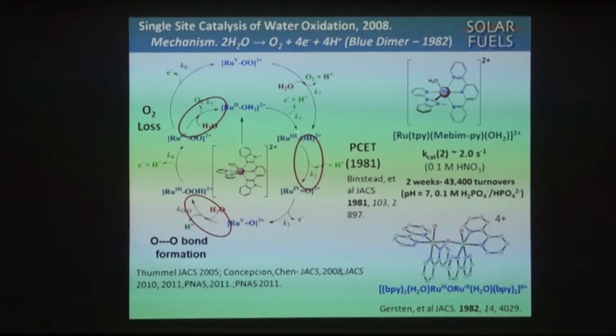One key to this, though, is that in the activation process to get to the active form there's no increase in charge. If you try that trick without having associated protons with a complex in this series, the difference in potential between the 2 couples would be between 1 and 1.5 volts. Proton-coupled electron transfer allows you to accumulate oxidation states without increasing charge, so you can build up multiple redox equivalents in one place. Anyway, ruthenium-4, if the thermodynamics are right, can do water oxidation. In this case, it's much faster to take away an additional electron to go to ruthenium-5, which, if you're a transition metal chemist, is now d3. And in most of these cycles, the rate-limiting step is next: oxo-atom attack on a water molecule, and I'll come back and say more about that mechanistically.